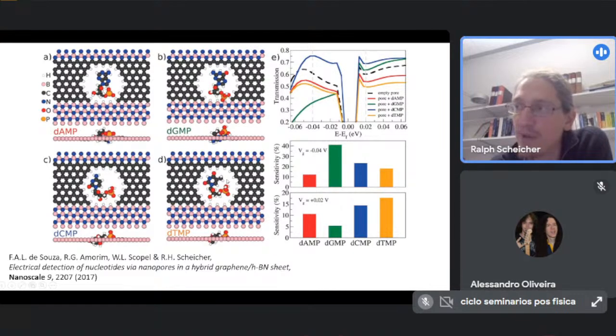So the different bases have different kinds of side groups. Some of them are negatively charged, some of them are positively charged, and that affects the conductance in a characteristic way. And so we can distinguish for certain gate voltages between the 4 different bases quite well with this setup. And this setup we have actually explored for many different cases, also for other molecules and so on. It's a very nice setup that has very high potential for sensing biomolecules and distinguishing between them.